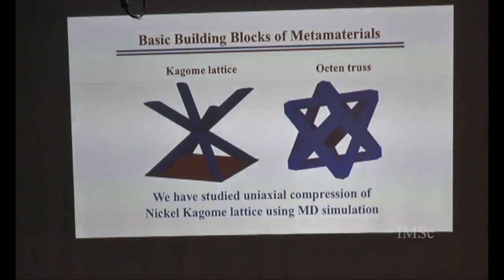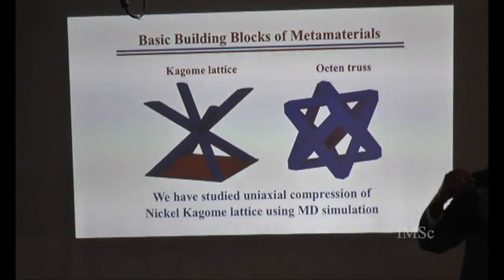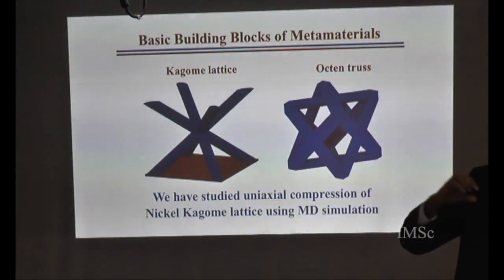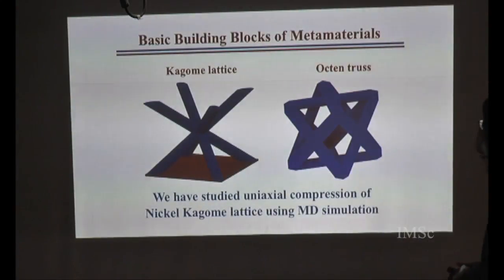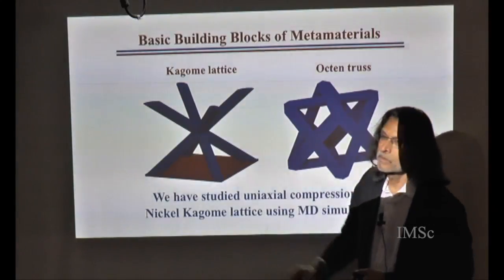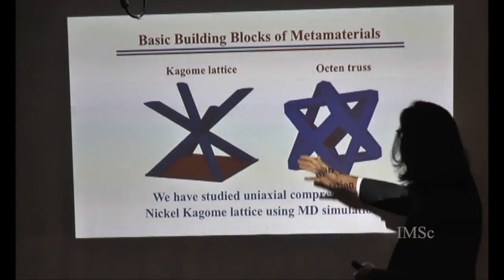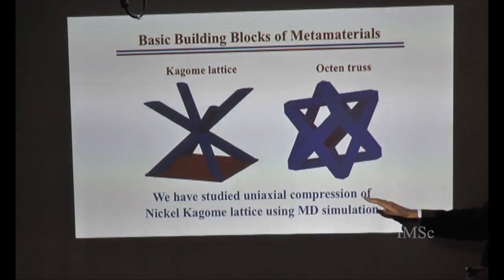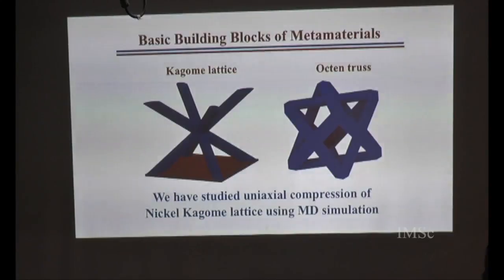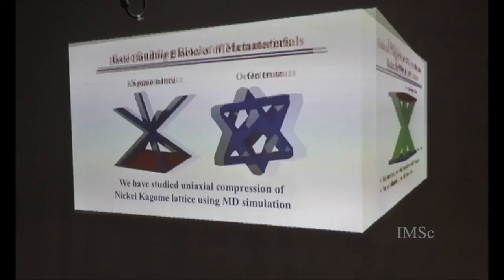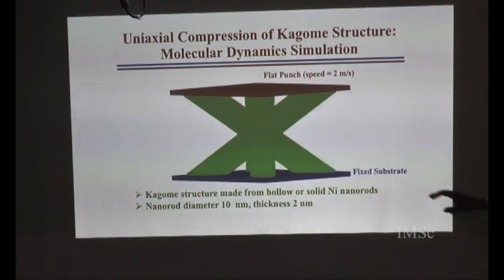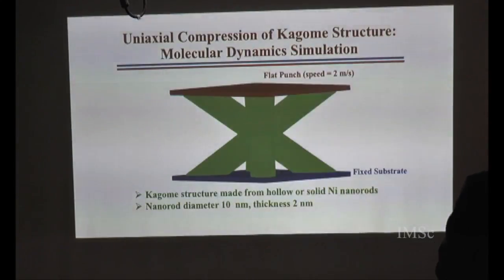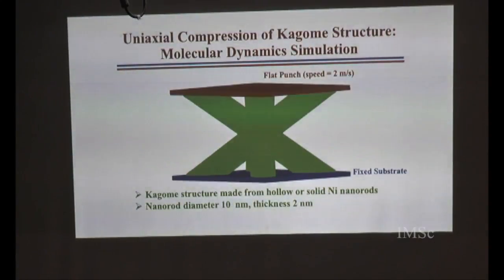So the basic building blocks the experimentalists are using are two kinds of lattices. They are made out of nickel tubes, nanotubes, and these tubes can be hollow or solid. This is one kind of lattice, called Kagome lattice, and this is another kind of structure. We have looked at this structure and its mechanical response to uniaxial compression. This is our structure, and we have used two kinds of nickel nanotubes. One is hollow and the other solid, and that's the only difference between them.